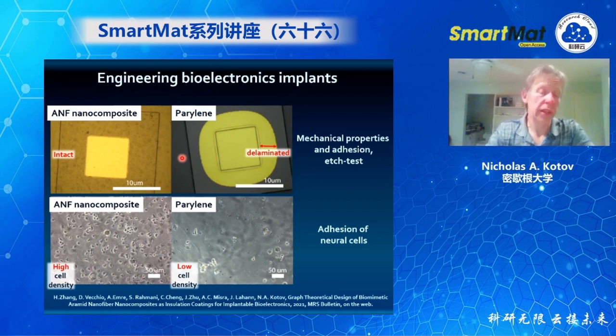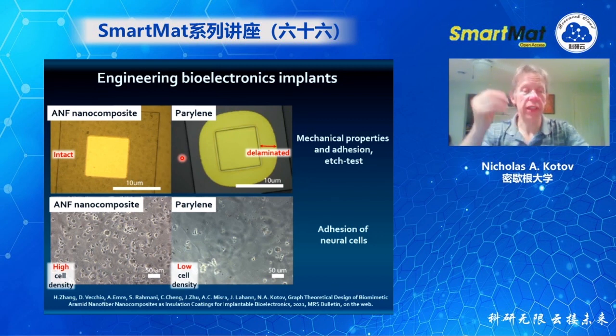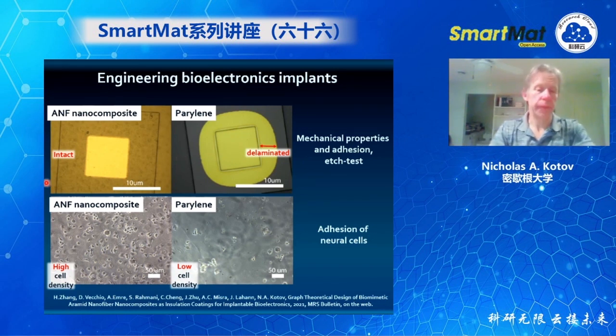The other thing is that the nanofibers, which originated from the organization of the cartilage and other connecting tissue, are actually the nanofibers from ECM, from extracellular matrix. Their geometry, their stiffness here is retained, and cells sense it. And for that reason, ANF composites are actually much better for adhesion of the cells.